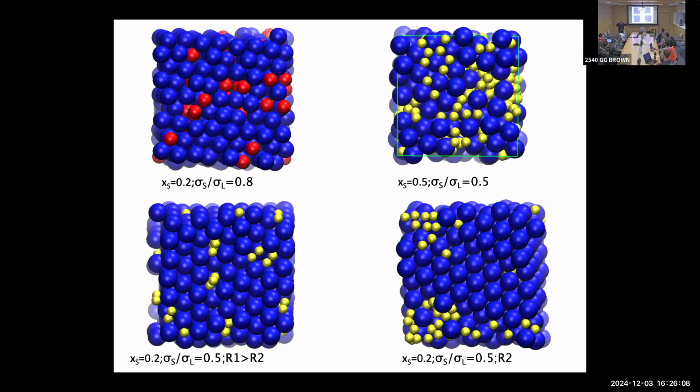So you're interested in what features determine this critical cooling rate. Getting back to what we originally started with, these purely repulsive particles, it's basically how things pack. If I have too few, like here's a majority species blue, and some minority species yellow, they're significantly different sizes, but there aren't enough of them to disrupt the crystallization. Same thing here. But then you get enough yellow particles of a different size, and it disrupts the crystallization. So this one is a good glass former. For these types of interactions, you cannot form glasses at 20% or 80%. You have to form glasses in the center, because that causes this frustration.